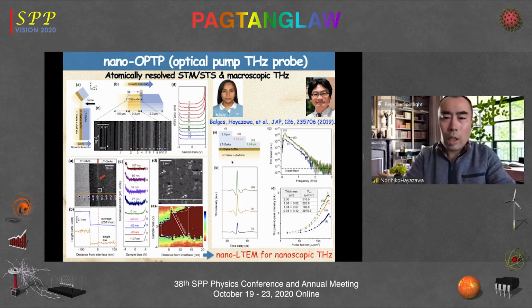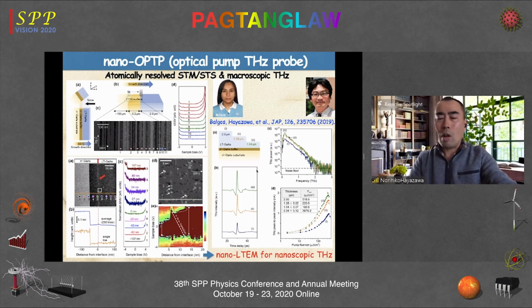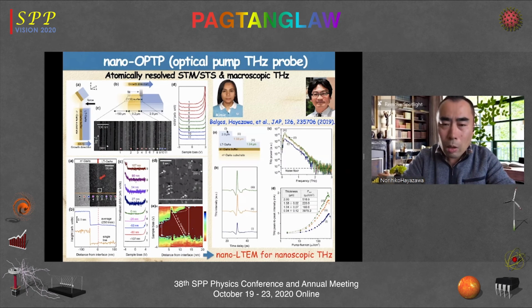But unfortunately, the terahertz microscope is a far field technique and diffraction limited, especially as the terahertz wavelength is quite long. That's why this is a kind of macroscopic characterization, although the STM studies have atomic spatial resolution. So in the future, what we are expecting is to employ nanoscale LTEM to characterize the terahertz emission property from the interface in the nanoscale, which can be compared with the atomically resolved STM characterization.